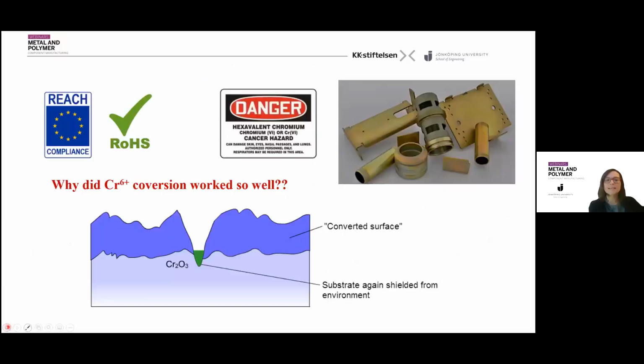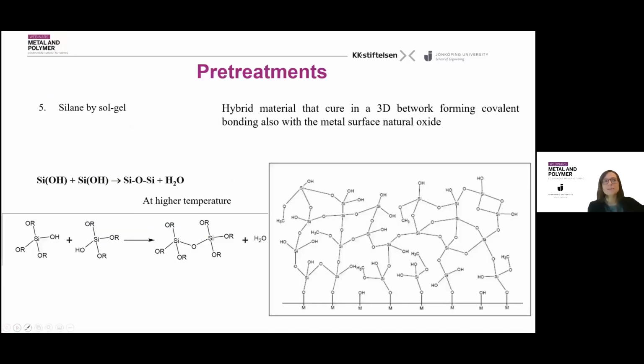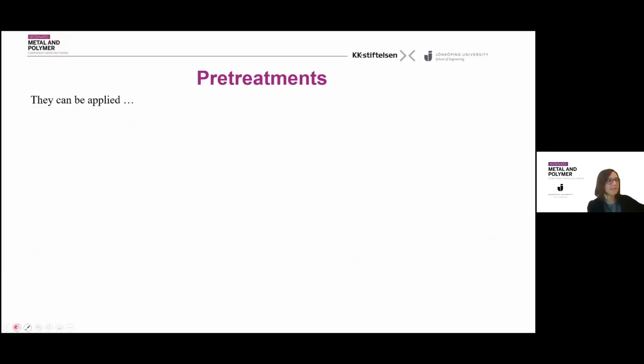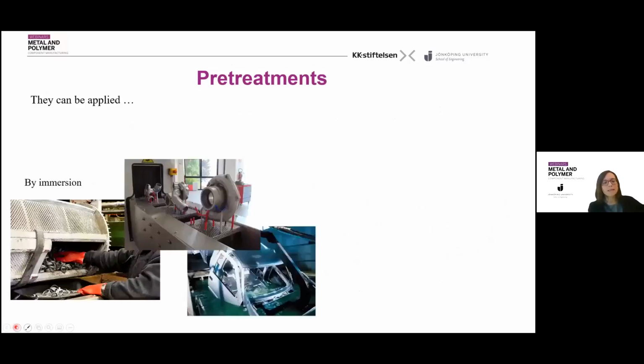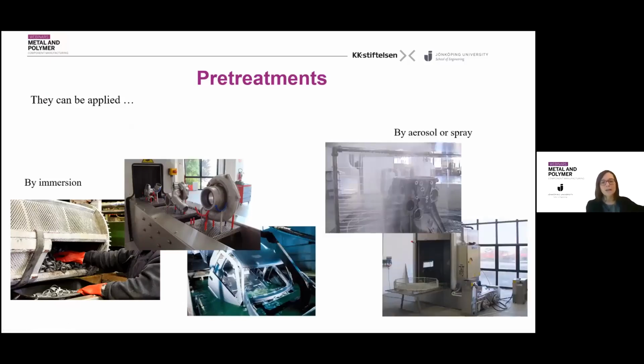In the other case, the other pre-treatments, of course, increase the adhesion, but also give some corrosion protection, passivating the aluminum surface. They can be applied by immersion, so all your components are immersed completely in a chemical solution, or by aerosol and spray.